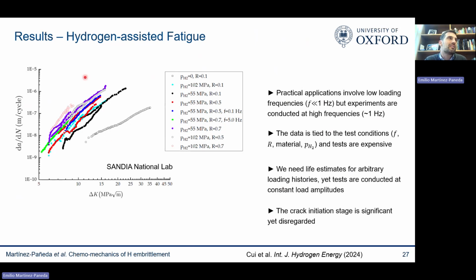Some data is out there. This is, for example, data from Sandia National Labs, where you see fatigue crack growth rate for different hydrogen pressures, up to 100 megapascals, different load ratios, and different frequencies. This data is very, very useful, but it has some limitations.